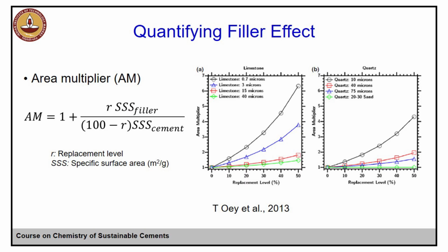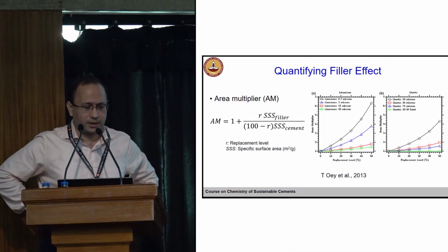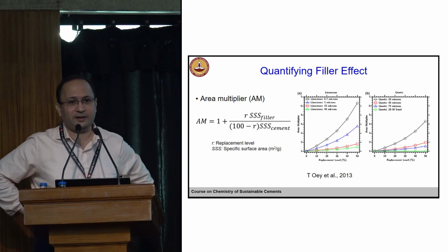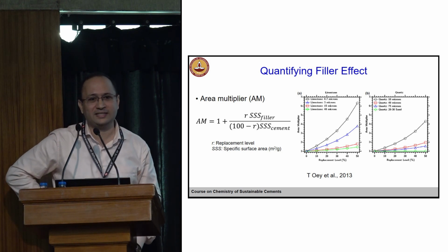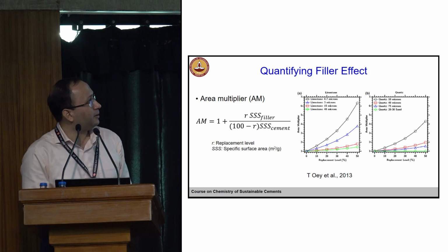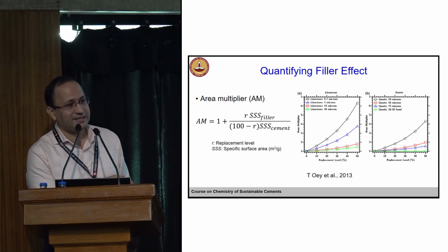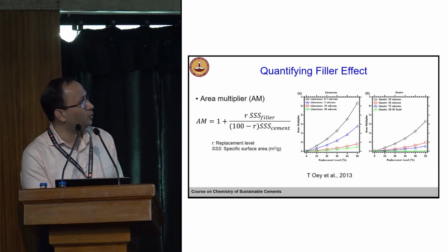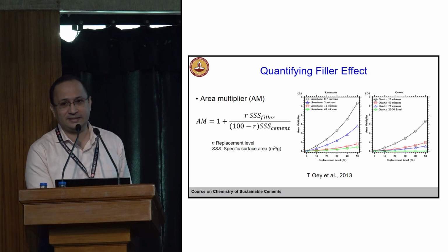So what could be a way? There was an interesting study done some time back where they looked at this area multiplier. That could be one way to quantify the filler effect. If we want to quantify the filler effect, let's say with limestone, for example, of different sizes, ranging from 0.7 micron to 40 micron. Can we compare these?